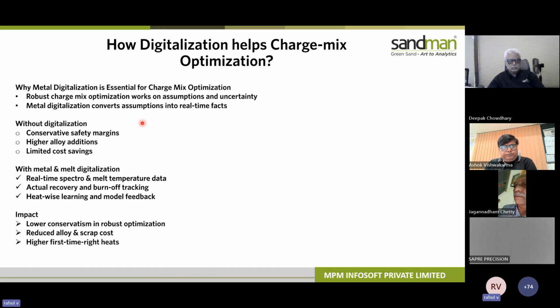Without digitalization, foundries have to be a little bit conservative in their safety margins, have to do higher alloy additions because we don't get the chemistry first time right. So we need to add alloys to make it up. Limited cost savings. But with metal and melt digitalization, we'll be enabling real-time spectro and melt temperatures. You'll also get an actual idea of the recovery of each scrap and the burn-off tracking, heat-wise learning, as well as box-wise learning, followed by model feedback. This way, we can be less conservative and more robust in our optimization, with reduced alloy usage and scrap cost, which will reduce our operational cost, and higher first-time right heats, which improves productivity.